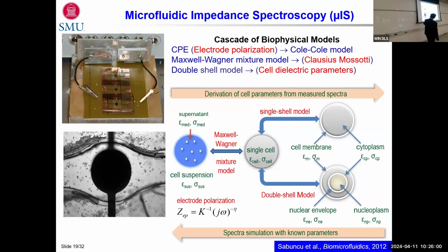And then we use the Cole-Cole model and Maxwell-Wagner mixture model, which separates the properties of the fluid and the cells itself. And that gives us the Clausius-Mossotti factor. And then you may go further in saying that this is a single cell. I would like to see a cell as a cell with a cell membrane and a cytoplasm, or a double shell model, which will also put a nuclear envelope and nucleoplasm in your measurements. So the key thing is that you have a complex frequency-based measurement of the impedance variation, and you have to model all of these things consistently to say something about the properties of the cell.